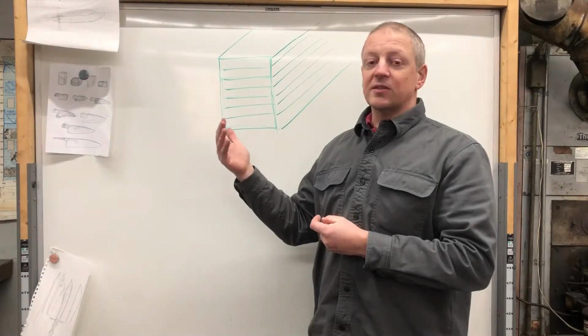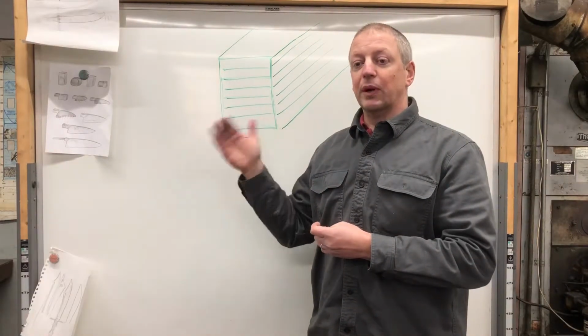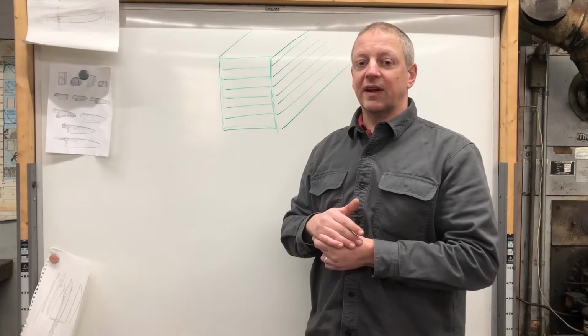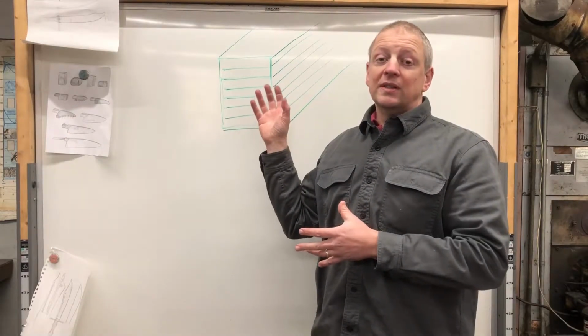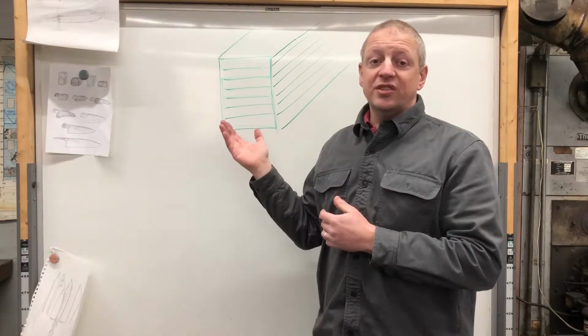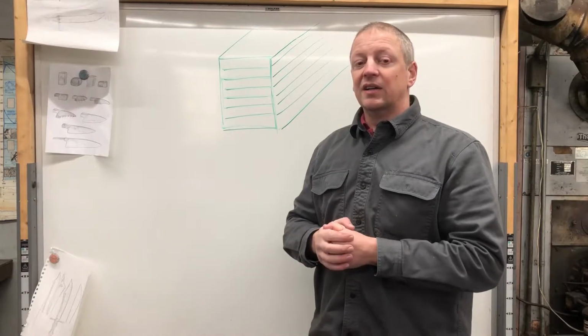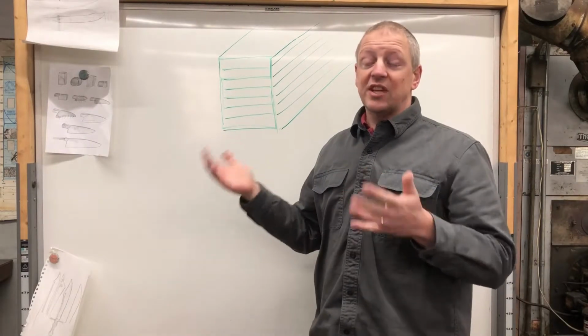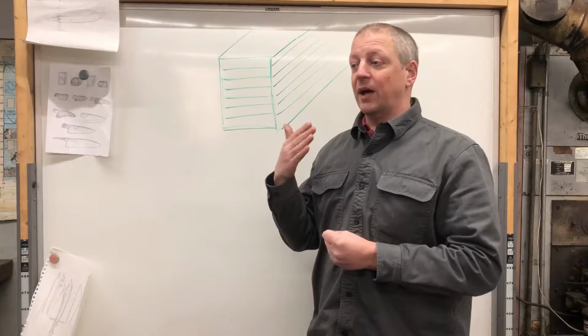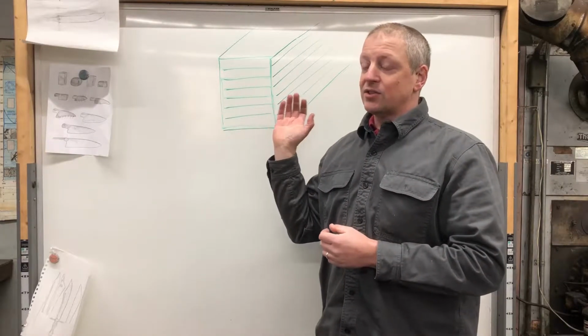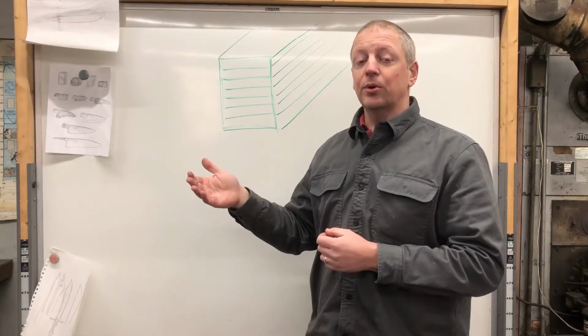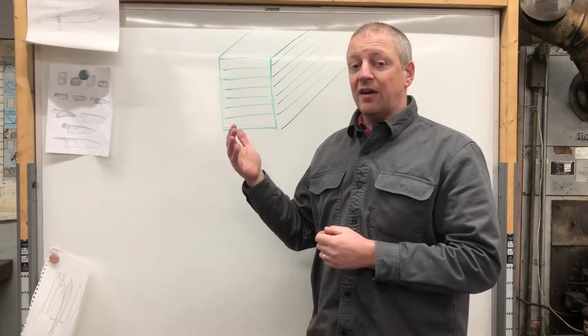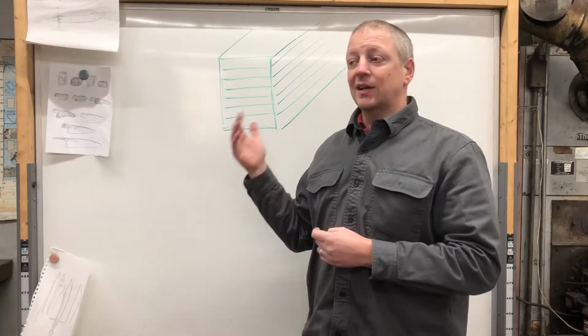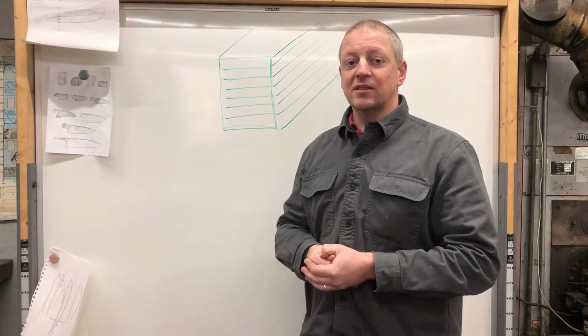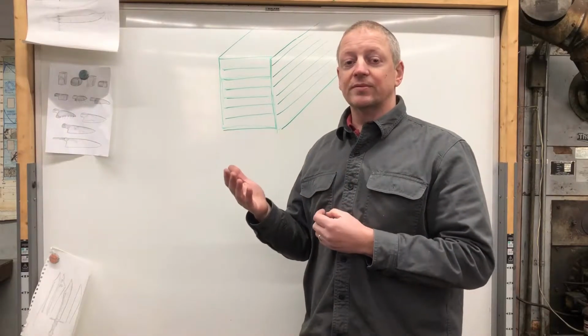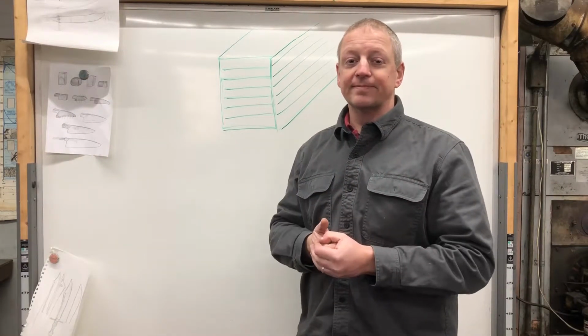The carbon coming to the surface is not capable of breaking down that compound effectively. So most inclusions are caused essentially by the flux. If you had left it as just a dry weld the whole way through, all you will ever have in there is iron oxide, and iron oxide is something that the steel can deal with itself, if you give it the right opportunities.